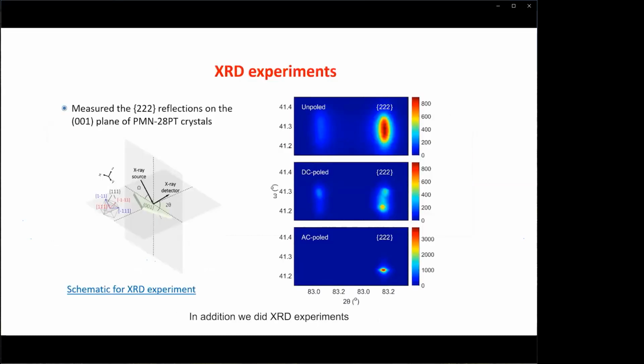In addition, we did XRD experiments to further check the results from the optical experiment. We measured 222 reflections for 001-oriented PMN-28PT crystals. As shown here, the AC poled sample shows a single and much sharper diffraction peak when compared to the unpoled and DC poled samples. This clearly indicates that the domain size of the PMN-PT crystal becomes larger after AC poling.